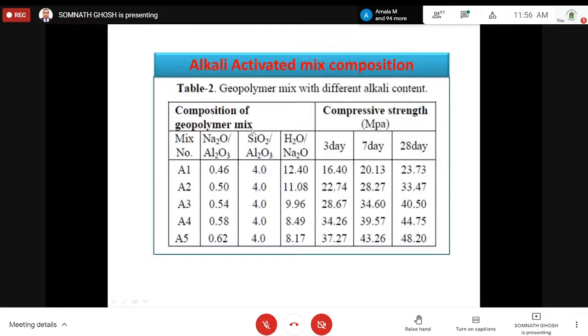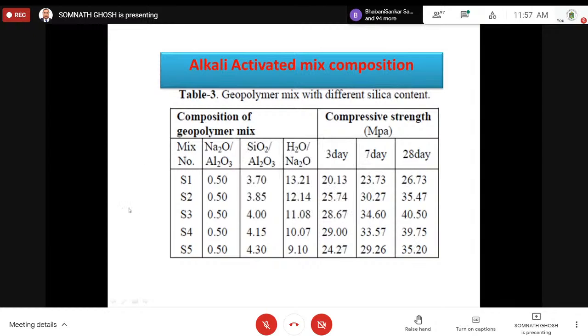Now you see, these results are quite encouraging. With fly ash, alkali and silicate at 28 days, just see how much strength you're getting. This 48 you can get after 3 days of heat curing also. See another set. Here also you're getting 35, 39, 40. Quite good. Of course, I have varied these things.